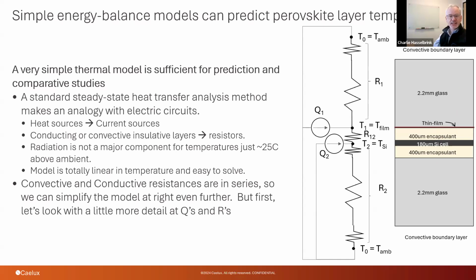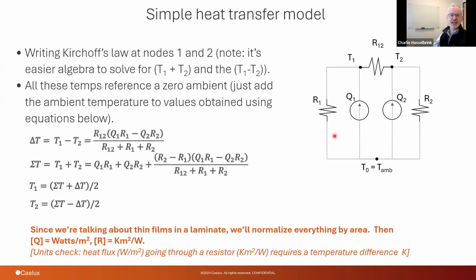You can take this circuit, by the way, and as you look at it, you can see I can just combine these two resistors, these three resistors, and these resistors, and generate a simpler looking circuit diagram that looks like this. And so here's the math. I won't go through it, but what you see very quickly is if you think that the temperature of the perovskite and the temperature of the silicon could be significantly different, then you have to argue that it must be because there's a lower resistance on one side or the other.